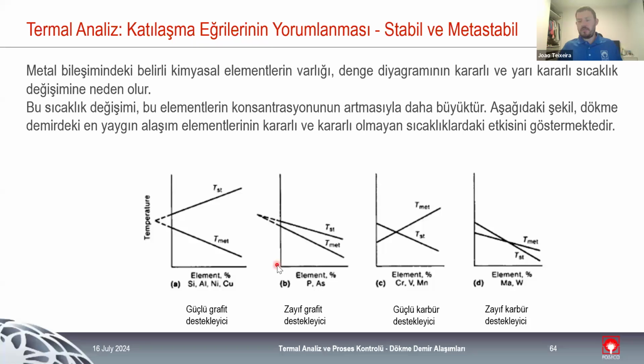And again, this is just for us to have an idea that different elements promote different types of solidification and affect differently the metal that we have. We have strong graphite promoters, so elements that are good for the transformation of graphite: silicon, as already mentioned, aluminium, as already mentioned again. We have elements that are not good for the formation of graphite, like phosphorus and arsenic. So we need to manage and we need to control these elements really carefully in the base metal.